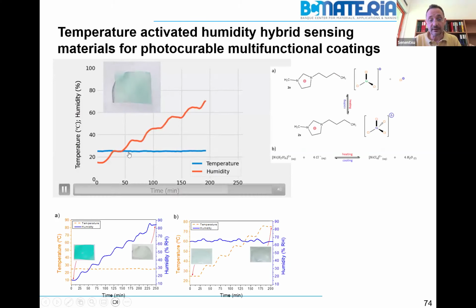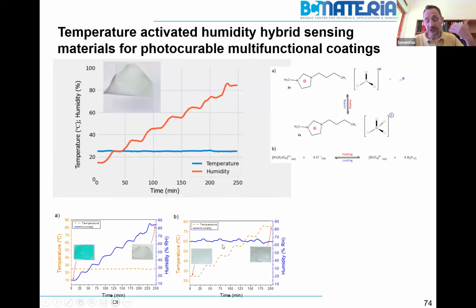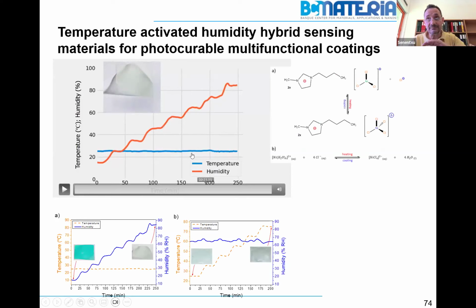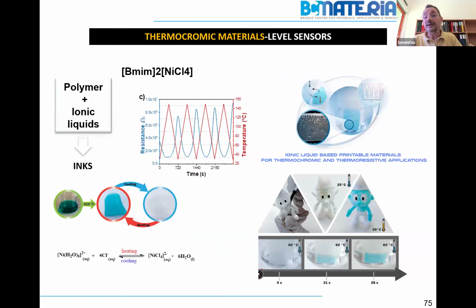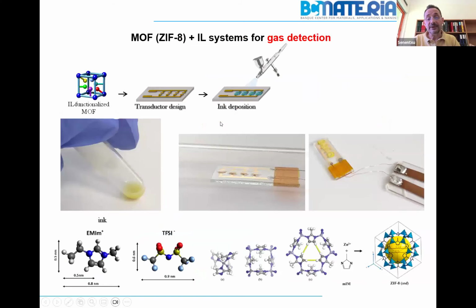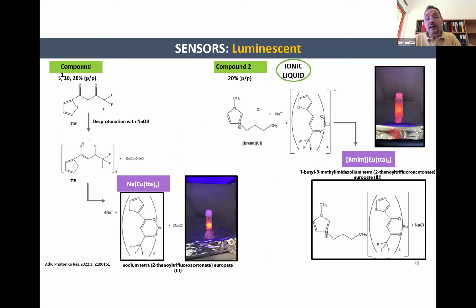This is thermal constant, the constant temperature, varying humidity, when you see the thermochromic sensor. Not only is, in this case, humectochromic, sorry, okay? Then you can do the opposite. You can tune the anion so that you have the opposite. For a given humidity, it senses the temperature. As they are ionic liquids, they have anions and cations. Most of them, they are not only chromic, they are also thermoresistive. So you can measure also accurately the electrical resistance of the system.